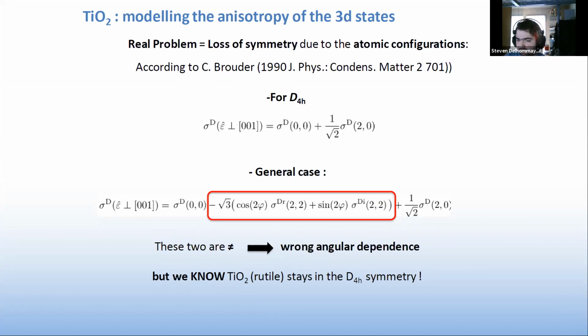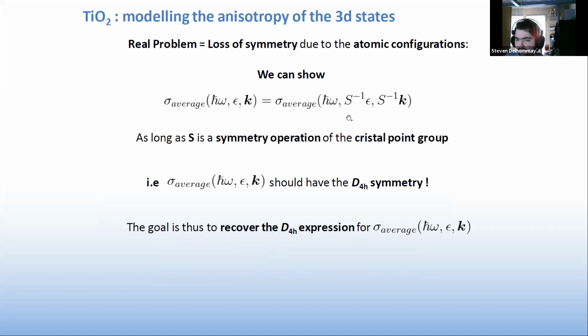And in fact, we showed it, because in this study, we managed to show this expression as long as S is a symmetry operation of the crystal point group. And what this means in English is that, very simply, the average cross-section that we calculate must have the same symmetry properties as the cross-section calculated for the D4h symmetry, which is the symmetry of the TiO2 rutile crystal. And so the goal from here is to recover the symmetry by adding and subtracting some terms.